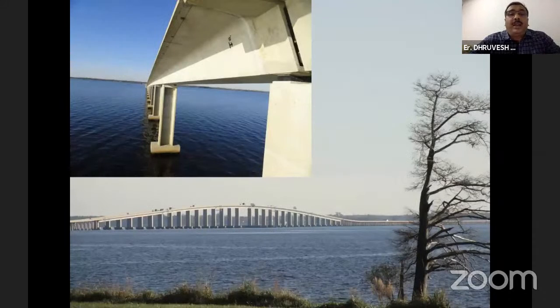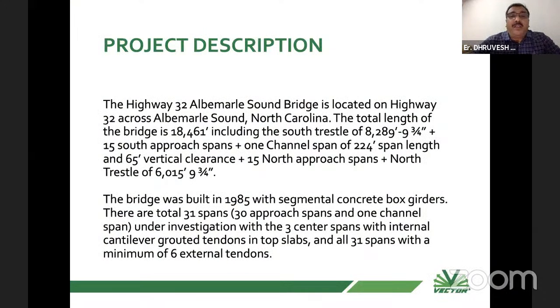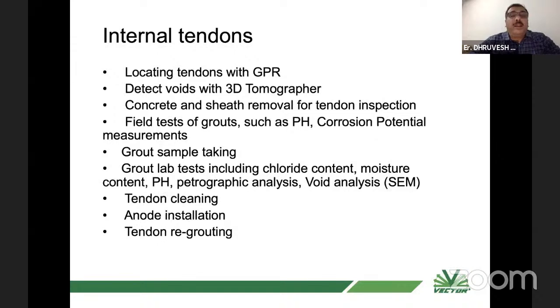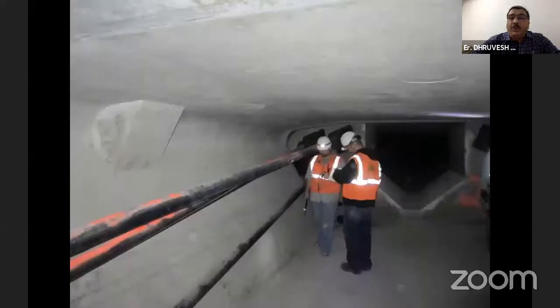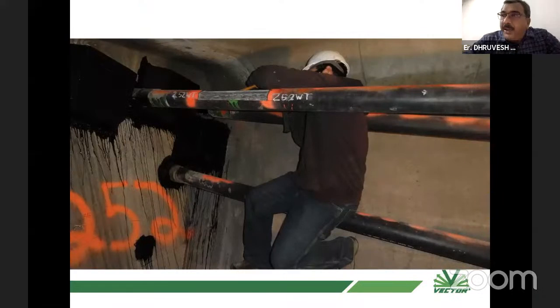This is one more case study I would like to show, wherein this highway bridge was built in 1985 and some spans. I don't want to go into much of the logistics, but the internal tendons were located using GPR, voids were detected, concrete and sheath removed for tendon inspection. We did all the tests, corrosion potential, pH, sample taking, everything has been done. And in this case particularly, what you can see is we found the voids and the tendons were accessible.